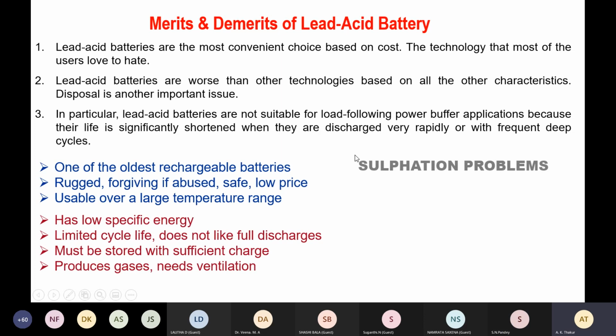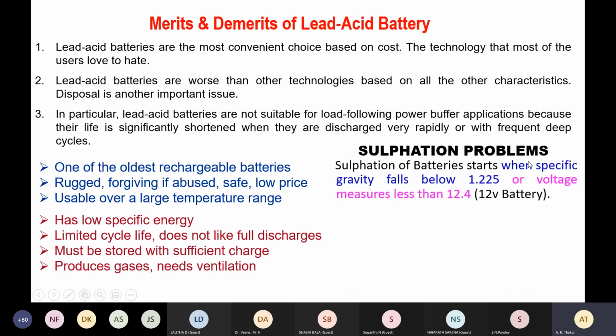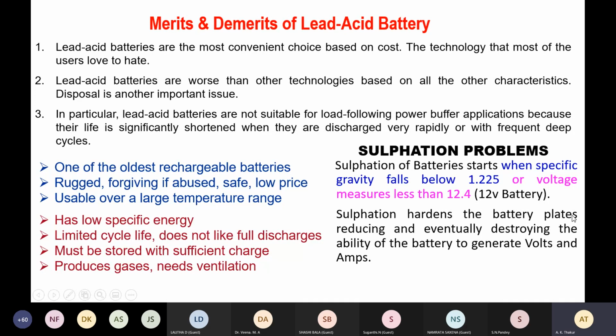So merits and demerits of lead acid. The biggest problem with lead acid is sulfation. Sulfur deposit occurs, and the greenish sulfate layers we always find in our vehicles are only because of sulfation. When deionized water inside the battery evaporates, and the specific gravity of the electrolyte falls below 1.225 for a 12-volt cell, sulfation occurs, and hence the cell starts giving problems with lower power, and this signals degeneration of the cells. Secondly, sulfation hardens the battery plates, reducing and eventually destroying the ability of the battery to generate voltage and current.